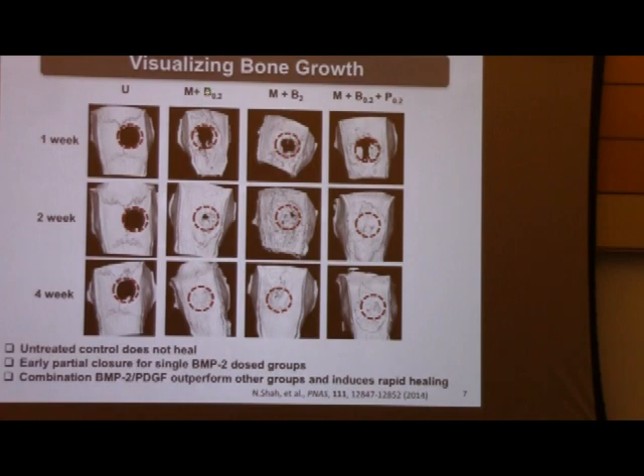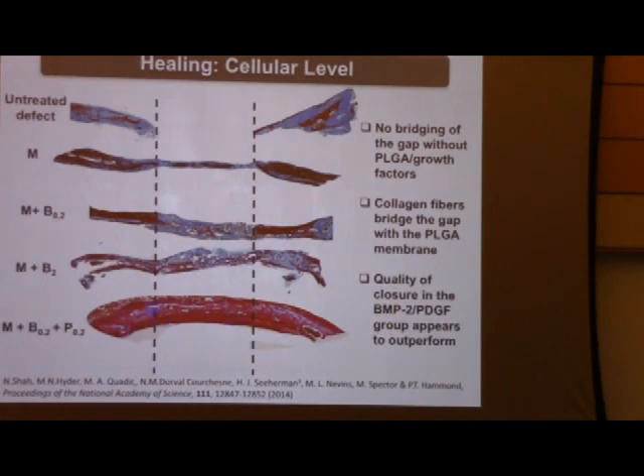So this is the first test. And we looked at 2 different doses of BMP2 by itself, 0.2 micrograms and 2 micrograms. We also looked at BMP2 at the low dosage with PDGF on top of it, again at a low dosage of 0.2 micrograms. And you can see that the bone fills in for all 3 cases, but perhaps just a little bit faster for the dual combination. If we, however, take a closer look, we can do histology.